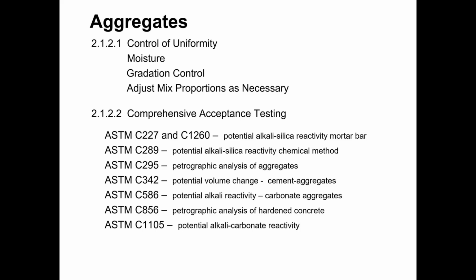Essentially what most precast plants do is a combination of those two things. Generally, we want to control the moisture content and keep it as consistent as we can, but at the same time, we're going to do regular moisture testing so that we know how much variation is occurring and we can account for that variation in the batching of the aggregates.